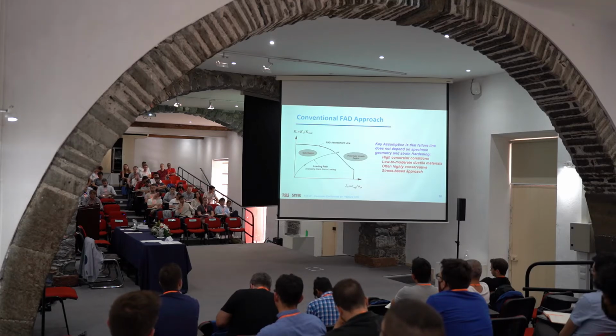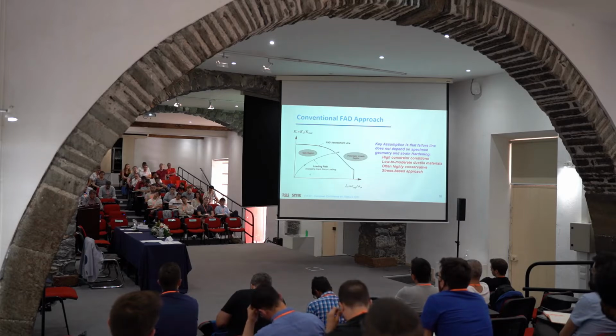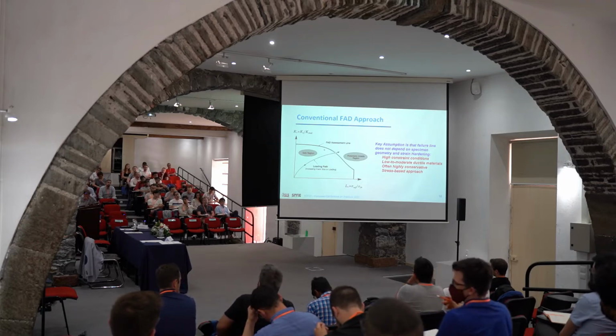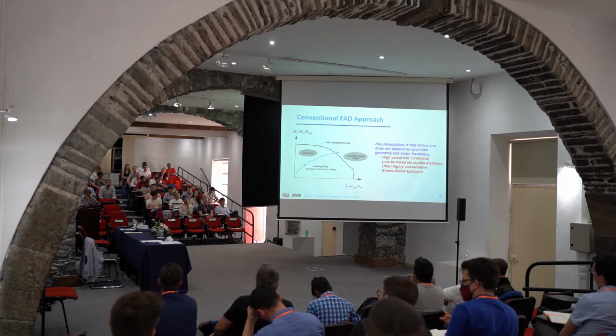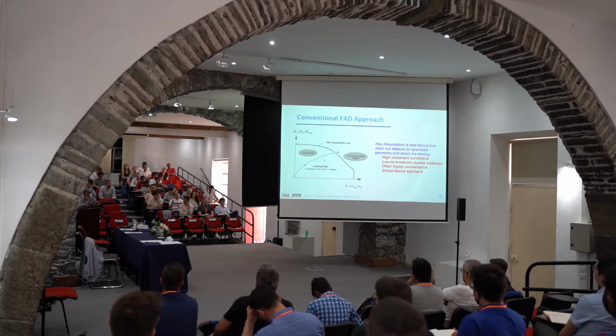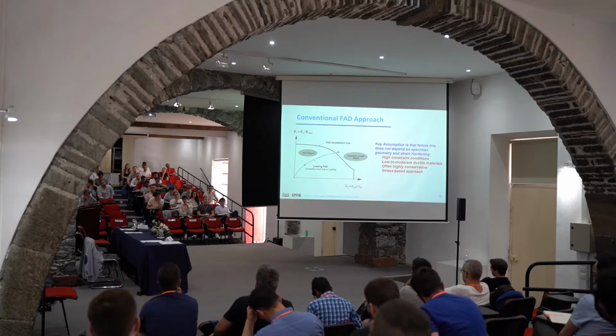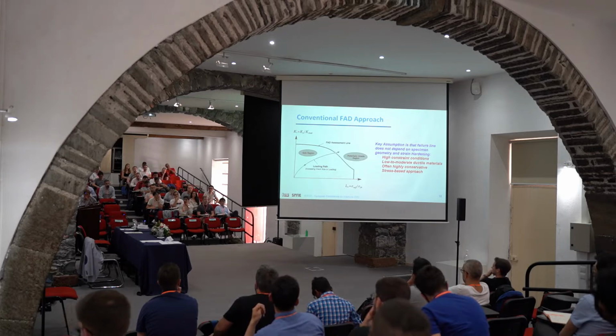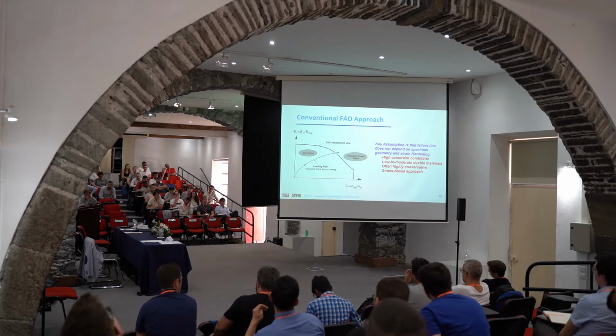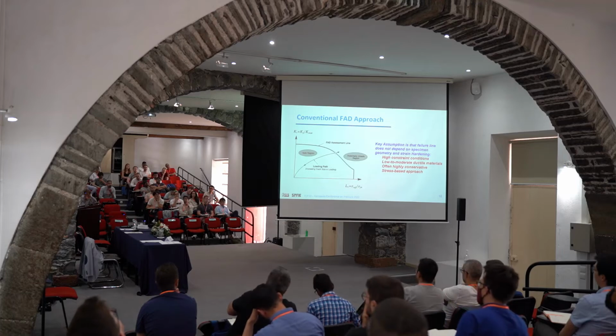And this is also very important. This is a stress-based approach. It's entirely based on stress, no strain. And I will show you why it's important that we also consider strain. And that's how it works. When you do your assessment, if you are inside this region below the curve, you are safe. That means your structural component containing a crack won't fail. If you are outside the curve or the region, this doesn't mean that your component will fail immediately.